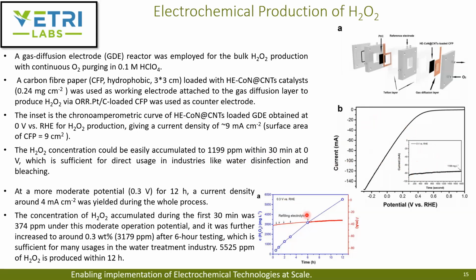Further, they calculated the concentration of peroxide accumulated over a 12-hour time span, not at 0 volts, but at a more moderate potential of about 0.3 volts. Initially they had a current density of about 4 milliamperes per square centimeter. The concentration of peroxide in the first 30 minutes was about 374 ppm, and it increased to 3179 ppm after 6 hours, finally reaching about 5500 ppm after 12 hours of peroxide production.